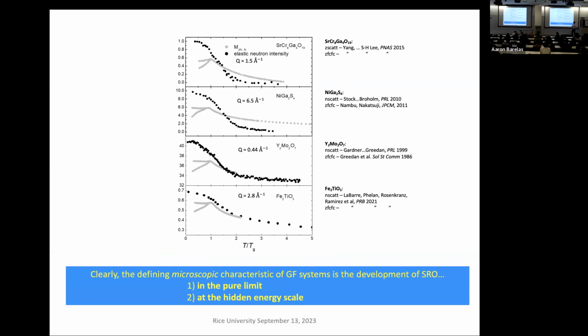So when you say development of short-range order in pure systems, in a spin glass there's no average order, but you have well-defined moments locally everywhere. So are you saying that in the pure limit of these models, you would actually find something like that, like a random non-zero spin texture at zero temperature? In the pure limit of what? In the pure limit of the new compound. Well, yttrium molybdate is stoichiometric, so is nickel gallium sulfide. Right, but especially in glass, there's some randomness. There's randomness that is most likely typical in oxide. It's just that we have an awesome impurity detector, and I'll show you why. It'll become apparent in just a few minutes, okay?